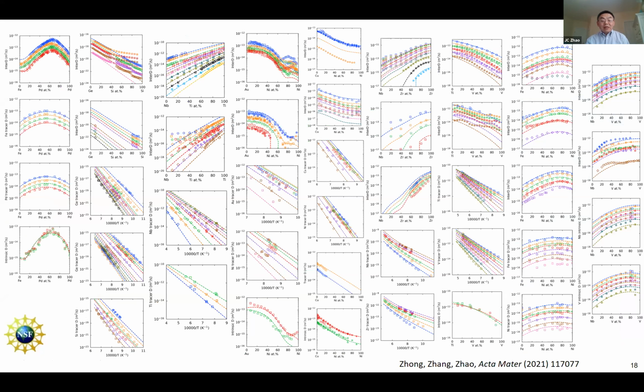And this is a snapshot of some of the systems. In this case, we used the interdiffusion coefficient data to fit the single parameter. And then we used that equation to predict the intrinsic and impurity diffusion, the tracer diffusion, and the intrinsic diffusion coefficient to within some order of magnitude. As I mentioned, this covers very diverse systems. All of them work.